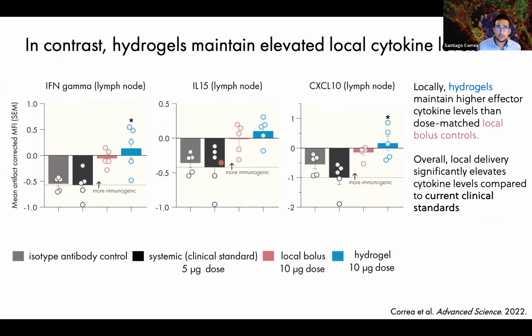Now, in contrast, when we look at the tumor draining lymph nodes, we see a different story. So let me remind you that this is looking at things 3 days later, 3 days after administration. And what you might notice is now we're seeing similar results for our negative control and our clinical standard control. And what that really indicates is how transient of an immunostimulatory response you see when you administer these antibodies systemically. That has to do with that antigen sink effect I was talking about earlier. That means that these antibodies are quickly depleted. In contrast, both of our local regional approaches are seeing elevated levels of these pro-inflammatory cytokines, with our hydrogels having a slight edge over the local bolus approach.